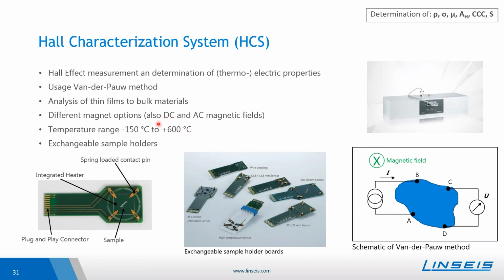Furthermore, one can also use DC or AC magnetic fields. The AC magnetic fields are especially suited for materials with a very low mobility, below 1 centimeter squared per volt second, because here the DC method just comes to its limits. So this can also be equipped with our Hall characterization system. Also, the HCS and the LSR1 have a further option, the illumination option, where it is possible to investigate the optical excitation in the semiconductor.